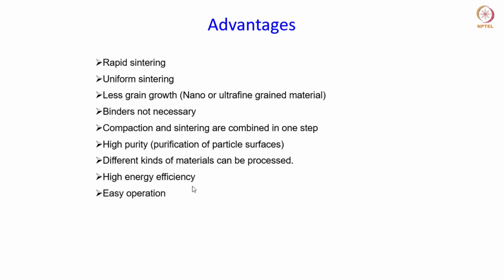Here binders are not necessary, unlike many of the conventional sintering processes where a binder is added to the compact to aid the packing of the powder particles. And compaction and sintering are combined in one step as the pressurization and heating occur simultaneously. And a high purity can be maintained here because of the purification of the particle surfaces, as we have talked about. When the spark is generated and there is local intense heating, it also leads to the purification of the particle surfaces by evaporation and melting.